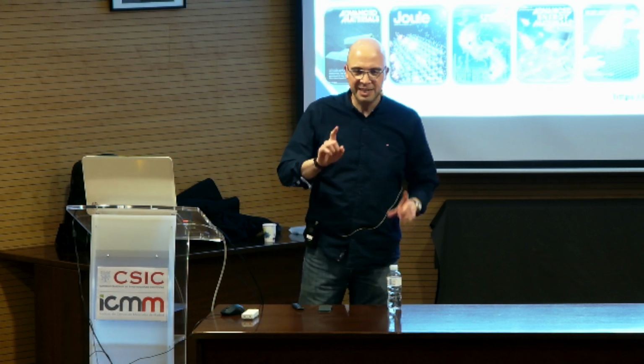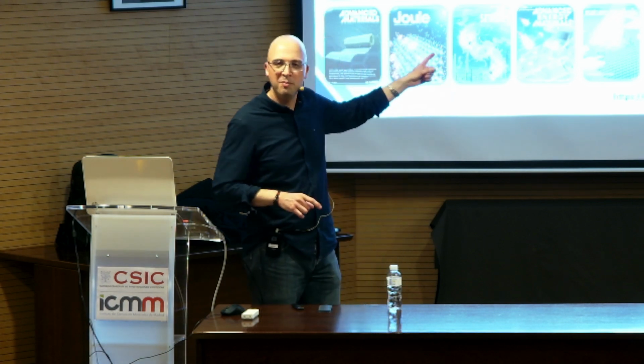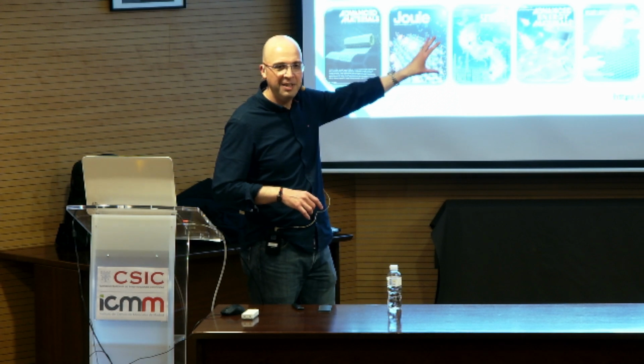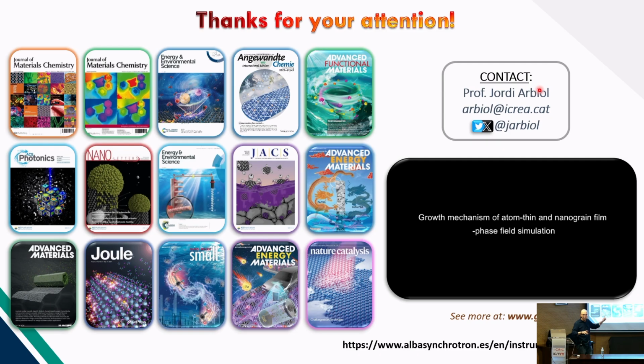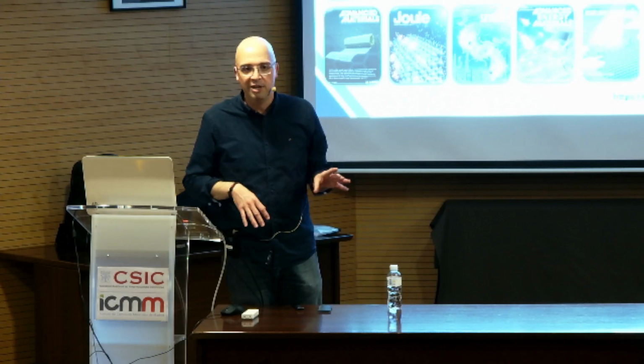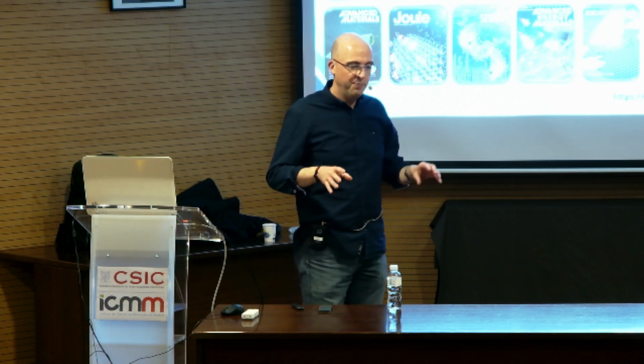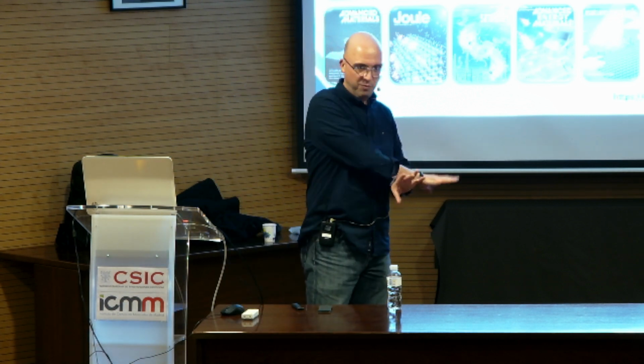I don't know if you remember, there were some images there where the atoms were moving. Exactly, so that's the point. When you are in the microscope, either you work at really, really low voltage, monochromating and doing your best not to affect the sample, or you get what I was showing. So the atoms are moving. You are reconstructing every one of the grain boundaries, and at the end, you don't really know what you are getting. So the only way to do it is focusing your sample far away from the grain boundary.